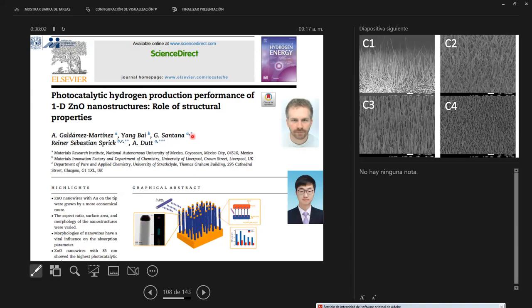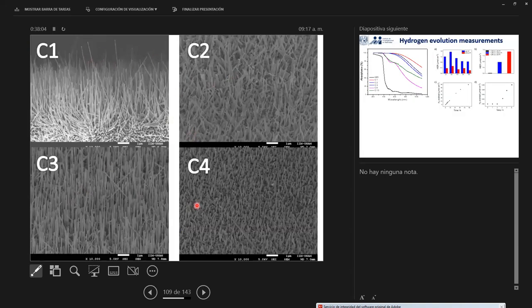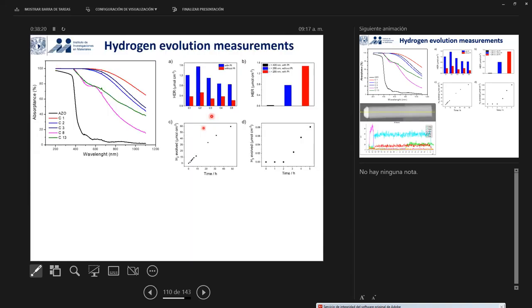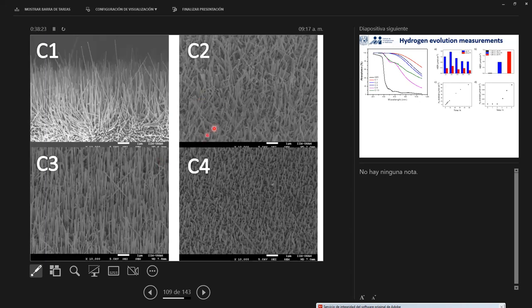And we found that we can grow different kinds of morphologies. Now we have control of the morphologies. We can grow longer nanowires, short nanowires. We can control the diameter. We can control the orientation. And we wanted to see, among these different structures, which one could be the best for the catalysis activity. And in the results, we found that this particular structure, C2, that is this sample, was one of the best samples for catalysis. Why? Because they have shorter nanowires, they have some kind of nanopillars also, and they are random again. So it seems that, compared to the vertical nanowires, a random nanostructure is again useful for catalysis.